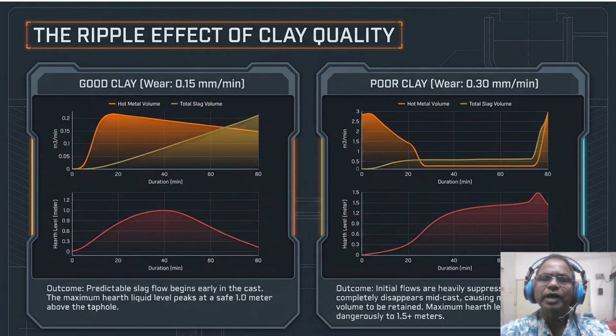When that level spikes, you are back in the ejector choke zone. So poor clay is not just a maintenance issue, it's a liquid maintenance and management failure that forces the furnace to retain massive residual slag volume, shortening your next window of operation. So if the clay holds and the flow is controlled, the final challenge is separating that liquid in the trough. So coming to the physics of separation.